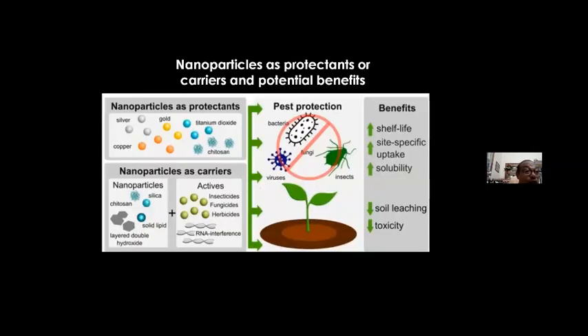Now, you can use nanoparticles as protectants also. We found that silver, copper, gold, and titanium dioxide nanoparticles can be used to protect against bacteria, fungi, viruses, and insects. Again, they can be used as carriers. For example, silica, chitosan, and solid lipid nanoparticles can be used as insecticide, fungicide, and herbicide carriers. So ultimately, what benefit will you get? The shelf life can increase, site-specific uptake can increase, solubility can increase, soil leaching can decrease, and we can decrease the toxicity also.